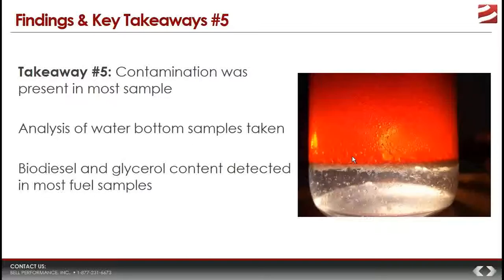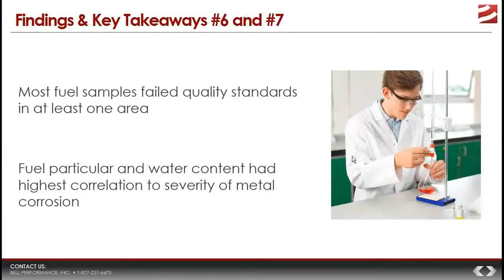And the reason why this matters is because when water, whether it's free water or dissolved water, comes into contact with biodiesel in these biodiesel blends, in this diesel fuel, it will interact with the biodiesel molecules, with the methyl ester molecules, and it will hydrate them. And that leads to hydrolysis chemical reactions, which break those biodiesel molecules apart, and they start to form things that you don't want in there, like chemical salts and soaps and peroxides. And those are things that microbes like to feed off of. So not only are they finding glycerol that microbes like to eat, but the simple fact that there's biodiesel in there means that any water that makes its way in there is going to break that down into other things that microbes like to eat as well.